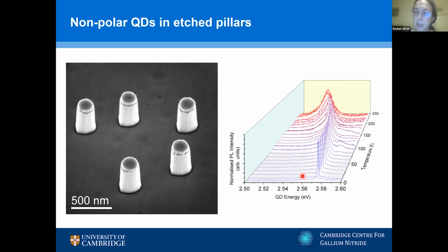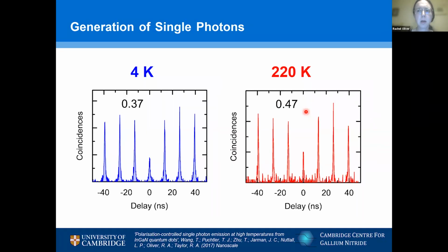From a dot here in the pillar, we can see very nice sharp emission at low temperature, broadening above about 140, 150 Kelvin, but we still have detectable emission up at 250 Kelvin. So compared to a typical arsenide quantum dot, really quite good temperature stability. Not as good as Mark Holmes and his ability to cook an egg, though, I have to admit.